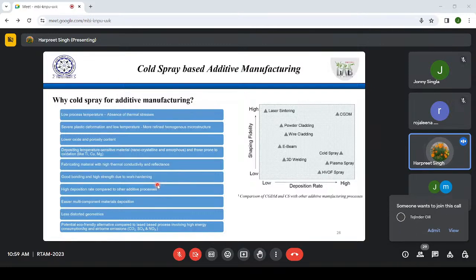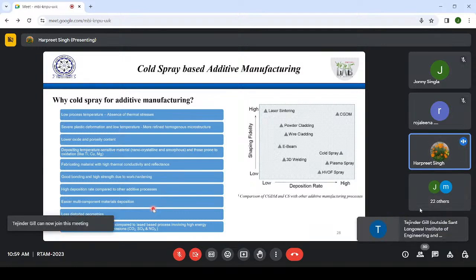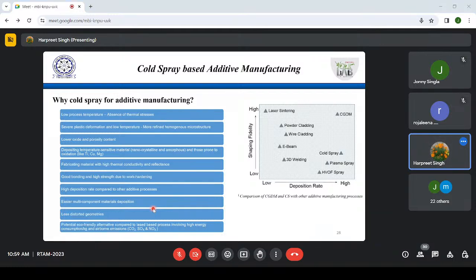Multi-material deposition. Now, this is another very important point, since there is a lot of emphasis on having composite materials, right? Suppose you have aluminum and silicon carbide, and you want to do it with laser sintering. What will happen? Both have different physical properties, like their melting temperature is different, their thermal expansion coefficient is different, and so on. So that will create a problem in laser processing, right? But in cold spray, again, temperature is not the problem. You can push those materials with a certain velocity and deposit them. So multi-component material deposition is not a very big challenge in cold spray, whereas it is a problem in conventional processes, especially where we use heat.